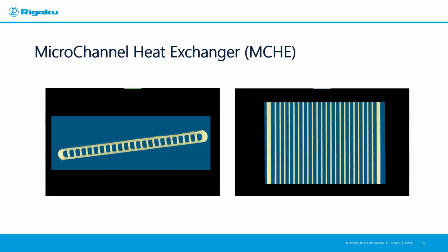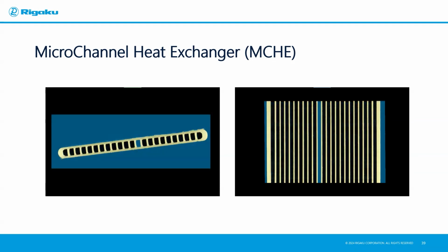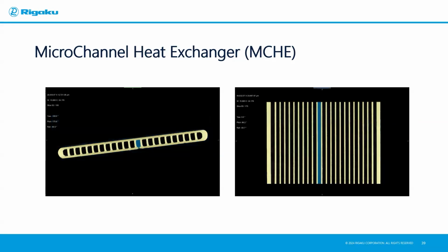But if what you really want to do is perhaps to get at the leak, then you can ask the question, which is the biggest individual segment that's connected to air? And that will be your leak. So in this case, what you see is this one section right here lit up that's connected to the outside air, and you can then crop everything out and just look at it in particular.